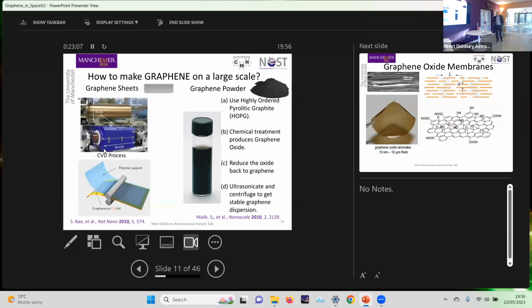Well, the graphene sheets are made by a process called chemical vapor deposition, CVD. And what they do is they take some copper foil. Copper is important because it acts as a catalyst in the process. You put it into a furnace at about 1100, 1200 degrees, and you pass a source of carbon over it. The source of carbon usually used is methane. So you pass some methane gas over it, and lo and behold, where you've got exposed copper, the methane breaks up and the carbon deposits on the surface as graphene. And when you've got the graphene deposited on the surface, the gas can't see the copper anymore, and so the process stops. So it's a self-limiting process for producing nice thin layers of graphene sheet material.